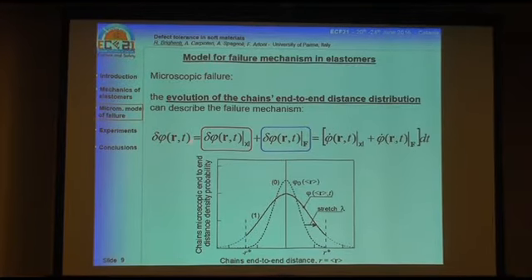We consider the variation of the distribution of the chain length. So we start from the initial state, phi naught here. We consider to stretch the material, and this has the effect to change the shape of this distribution. So we have, for example, an originally chain with length r, which is more stretched, so it increases length, while the opposite occurs on the other side. We are considering a vector, so we have positive and negative vectors, let's say. And we can say that we can have failure, for example, if our chain reaches a length which is above a given r star length that we define later, and then can give rise to the break of the chain, so this chain does not contribute anymore to the energy of the system.